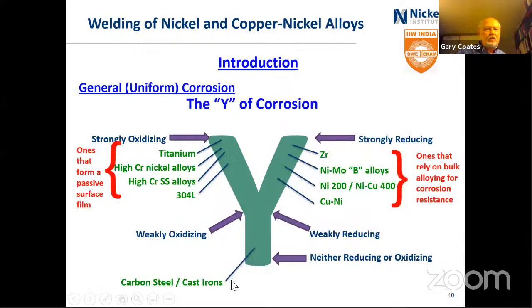And of course, as you can imagine, the chemicals that are strongly oxidizing, you want to have a passive surface film. For stainless steel nickel alloys, you want the chromium in there, but titanium falls into that category. It forms a titanium oxide protective layer. And then the stainless steel and nickel alloys that contain chromium do well in the strongly oxidizing conditions. In strongly reducing conditions, those alloys don't do very well at all. Zirconium, the nickel molybdenum B alloys, the pure nickel, the nickel copper alloys, and the copper nickels all work well in reducing conditions there.